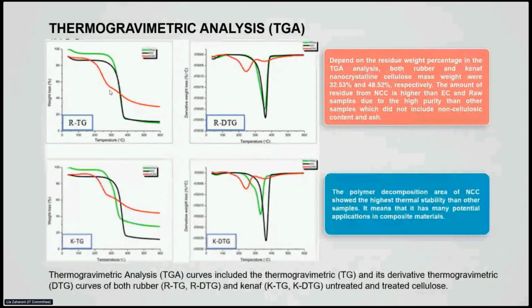TGA analysis. Depending on the residue weight percentage in the TGA analysis, both rubber and kenaf-based nanocrystalline cellulose residue weights were 32.5 and 48.5 respectively. The amount of residue from nanocrystalline cellulose is higher than extracted cellulose and the raw samples due to the high purity compared to other samples, which did not include non-cellulosic content and ash. The polymer decomposition area of nanocrystalline cellulose showed the highest thermal stability of all samples. It means that it has many potential applications in composite materials.